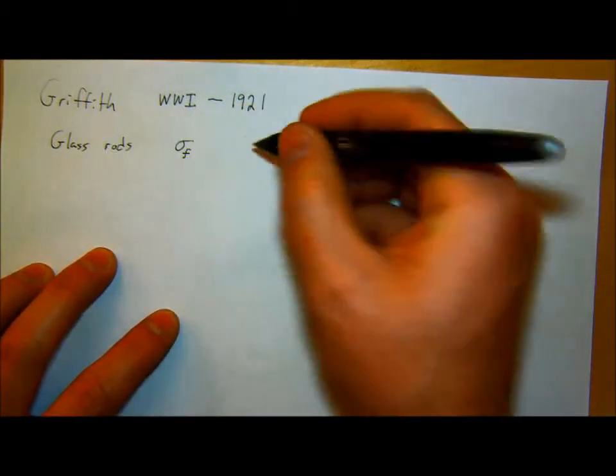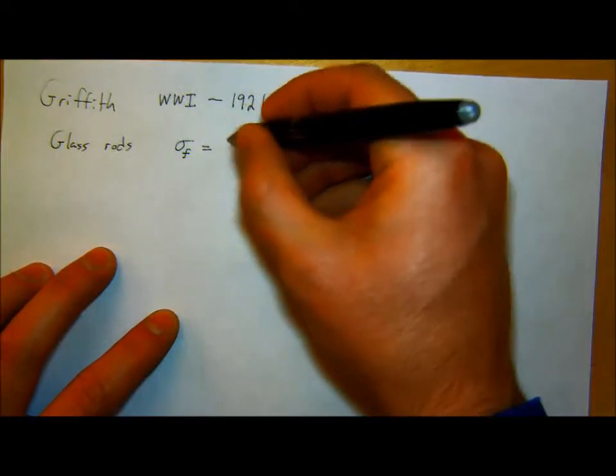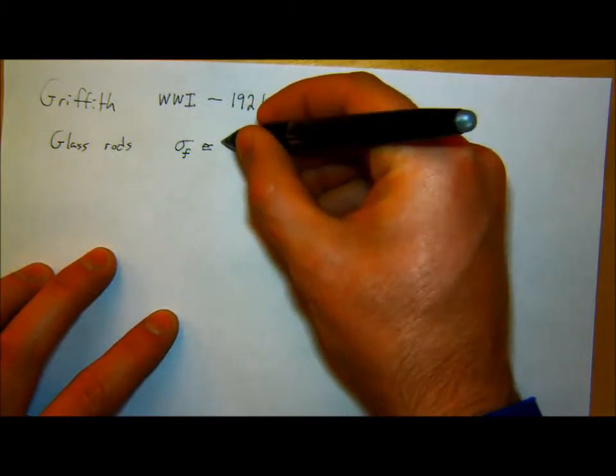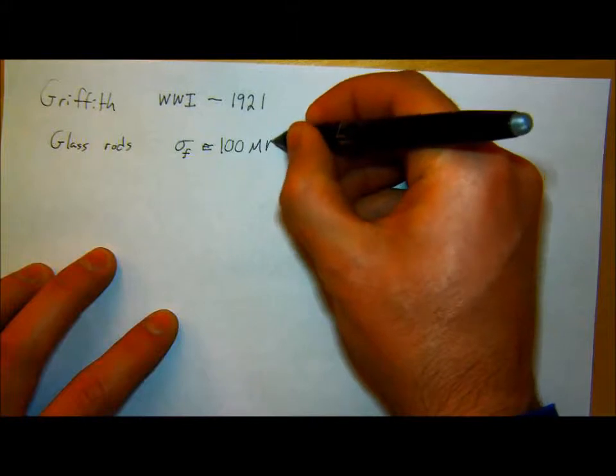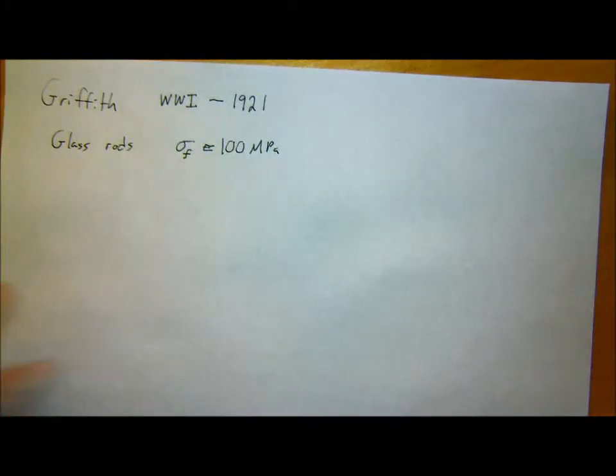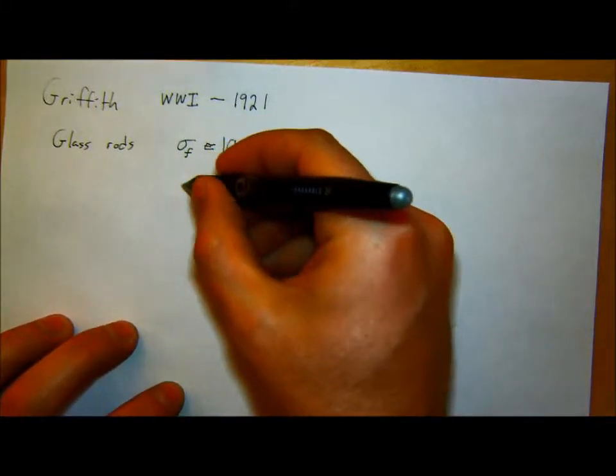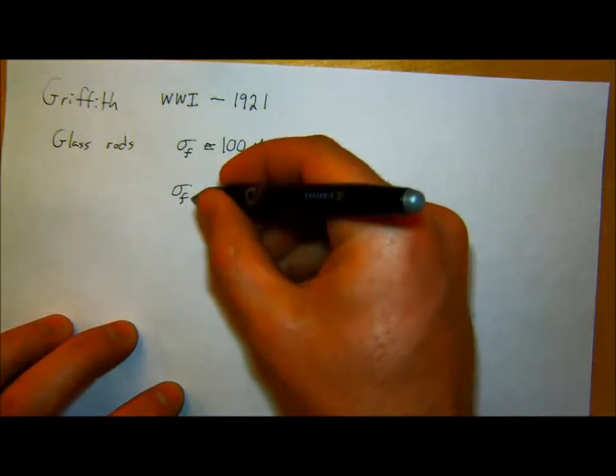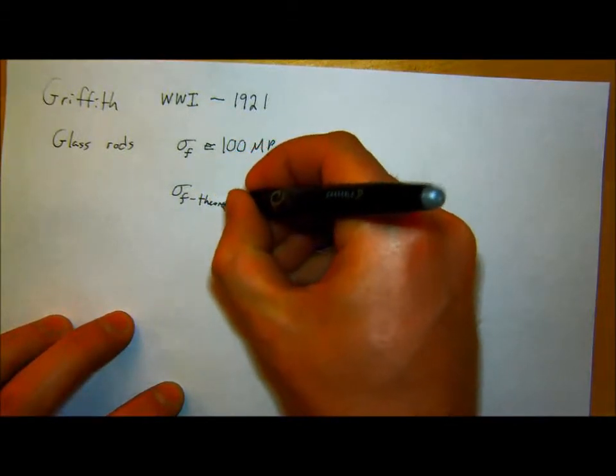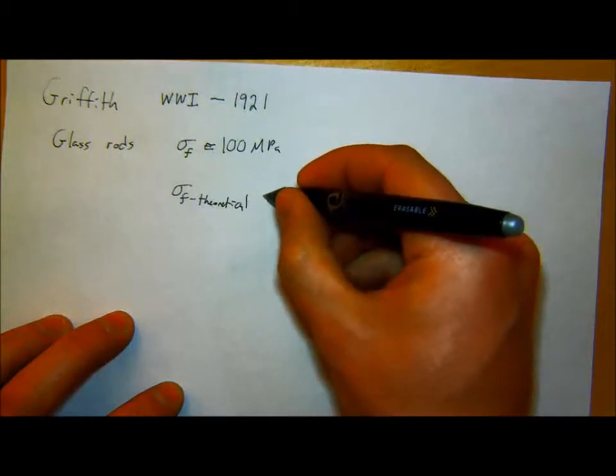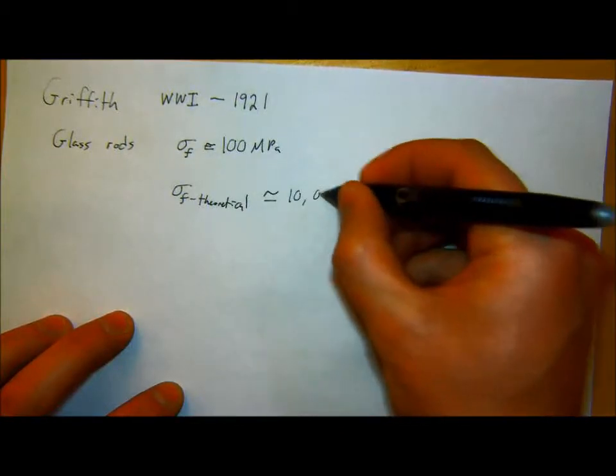But he knew theoretically, from the amount of stress you have to apply to break the atomic bonds in glass, which had been done a while before, that this should be closer to about 10,000 MPa. So he saw this discrepancy. He said, okay, theoretically this is supposed to be like two orders of magnitude higher strength than what we're seeing. So what's going on?